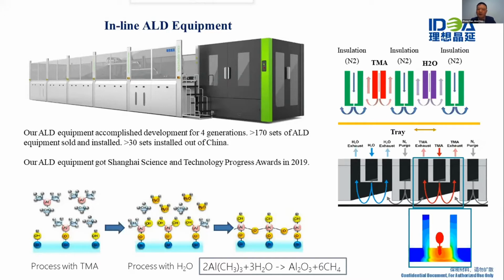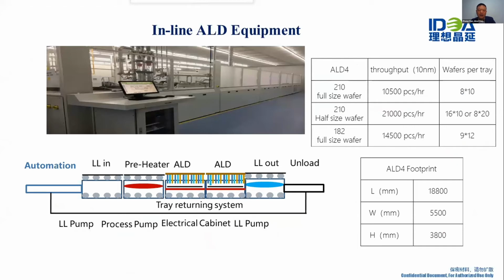Although TMA and water can build very good quality aluminum oxide film, it can also cause some wraparound to the other side of the wafer, and PERC and TOPCon solar cells do not want wraparound aluminum oxide residue on the other side of the wafer. But because of our inline working mechanism, our ALD equipment does not have this wraparound issue. As you can see from this data, our inline ALD equipment has a very high throughput. For 182 wafers, we can make 14,500 pieces per hour. For 210 wafers, our throughput is 10,500 pieces per hour.